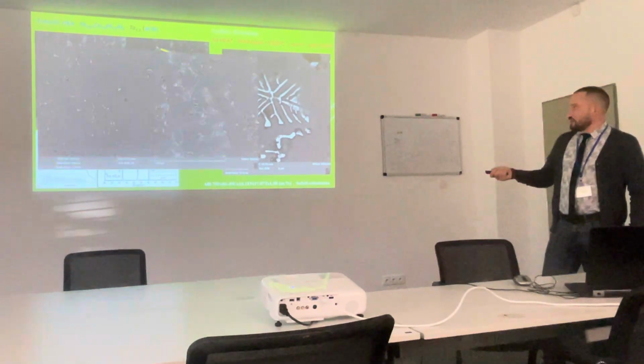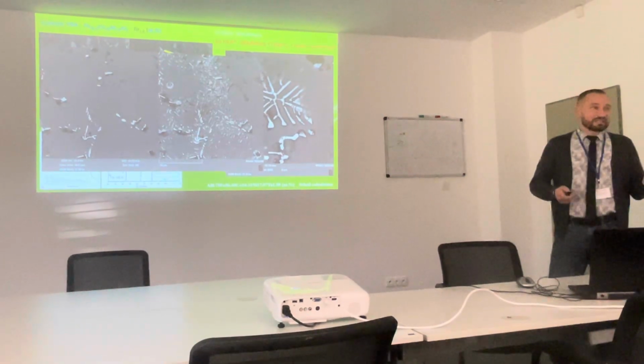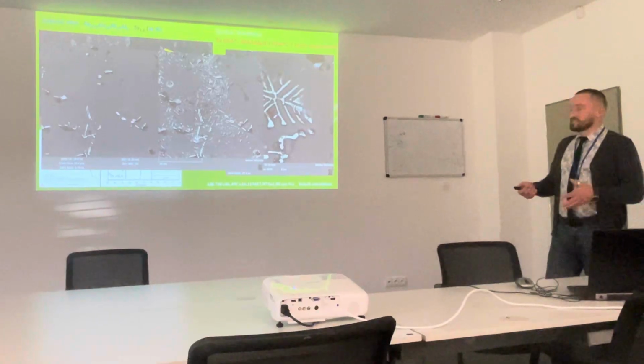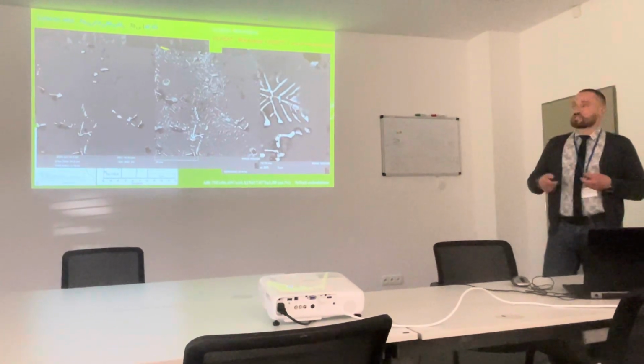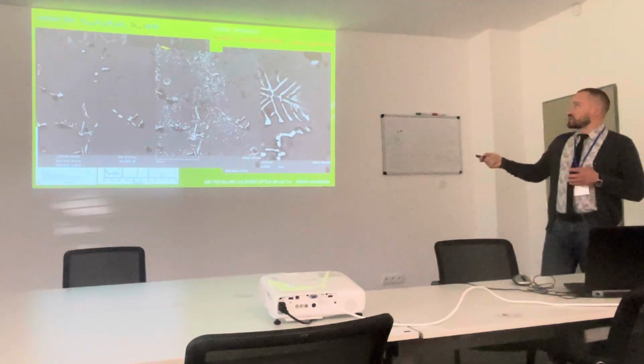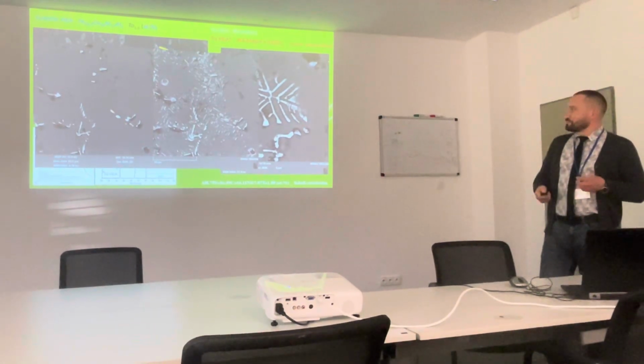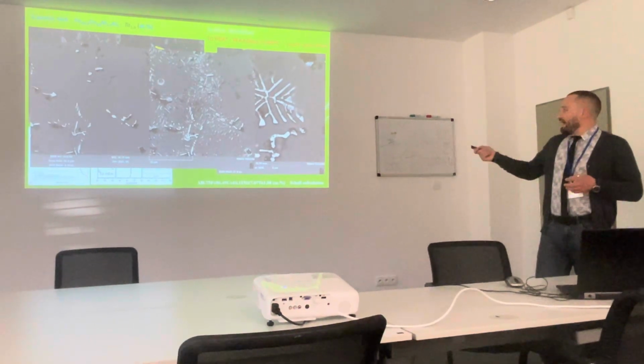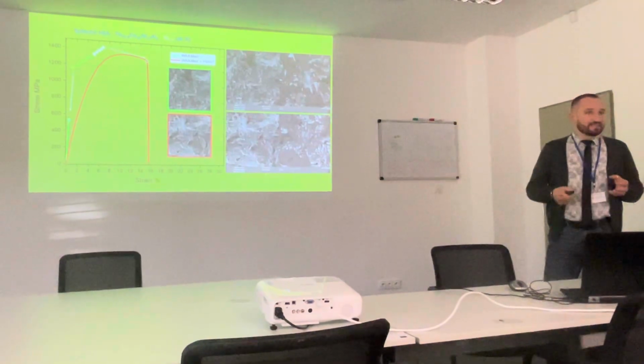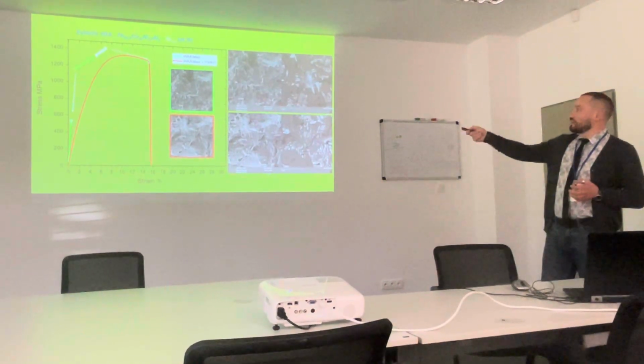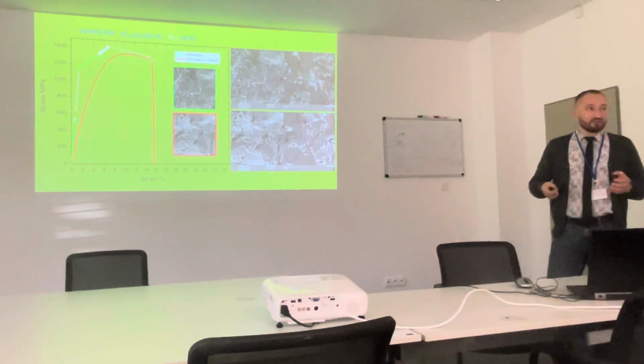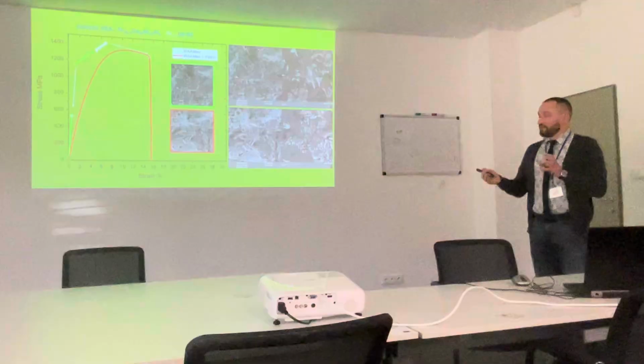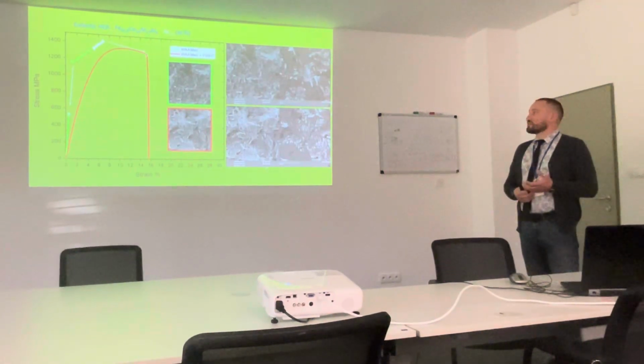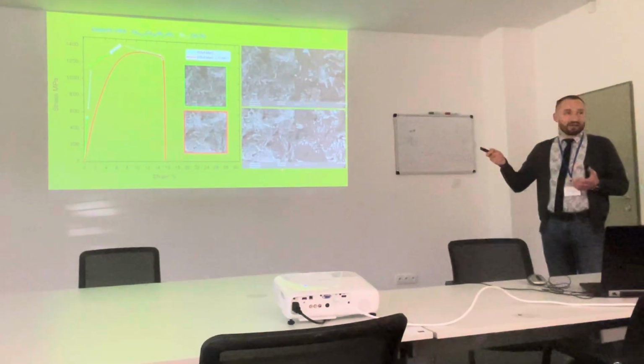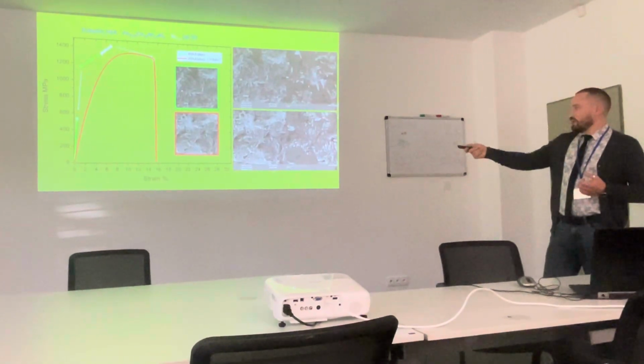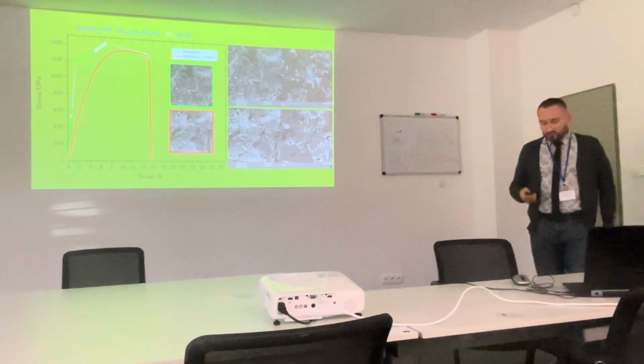We performed heat treatment of this material at 1000 degrees of temperature for 1 hour, and after that quenching in water. We obtain dissolution of the excessive phase, actually a composition of tantalum with another element. And we obtain a significant increase in plasticity while conserving a high level of strength. In this case, we have printed a volume sample of high entropy alloy with yield stress up to 1300 MPa and elongation to failure up to 15%. It's really good results.